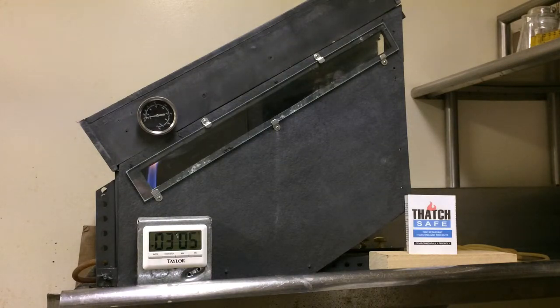This test method provides a relative flame spread of the coatings using small test specimens. By calibrating the 2-foot tunnel, this is the Monsanto tunnel that we are using today, with test method ASTM E84, the results obtained by this test method are indicative of those obtained with the large-scale specimen in the test method ASTM E84 UL 723.